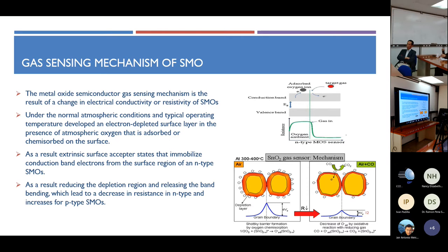Now the gas sensing mechanism of the metal oxide semiconductor. Basically, when you keep the material in the atmosphere, the oxygen reacts with the material, is adsorbed on the material surface and extracts electrons from the material. So a space charge layer is formed, and that barrier is called a Schottky barrier. Because of the Schottky barrier, the resistance increases. Because there are not enough free electrons in the material, the conductivity will be very low.